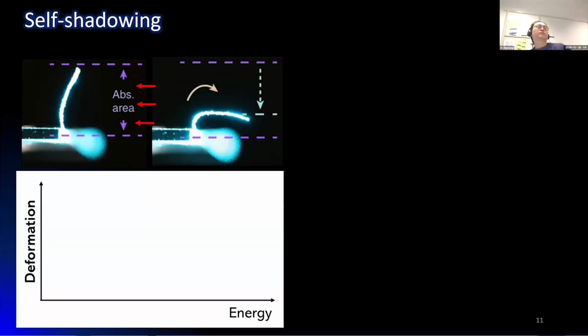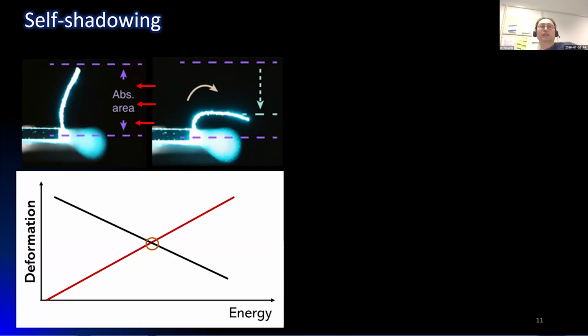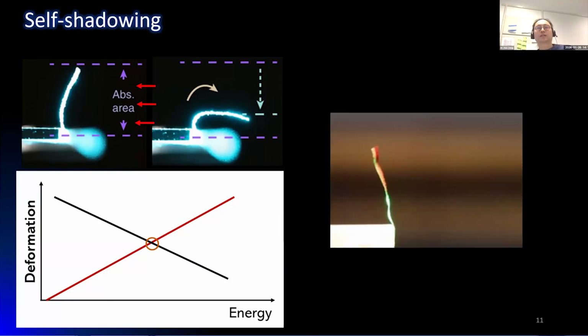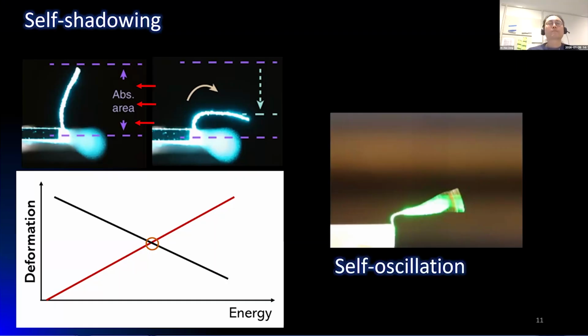So what you can expect is that if you increase the light intensity, the light energy, more light energy, you have bigger deformation. But once the strip bends, it blocks the light. It reduced the light absorbing area. So due to the deformation, it actually reduced the energy intake. So you may guess that there should be one middle position that it is settled. Maybe half of the light will be absorbed, half of the light will be just passing through. So there should be one equilibrium position. But in fact, not. It does not want to stop. It will keep oscillating around the middle position. And it self-oscillates.